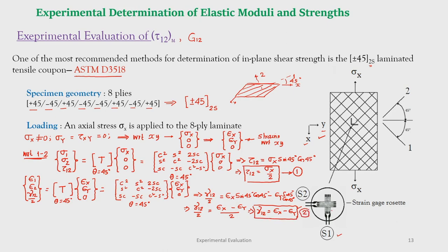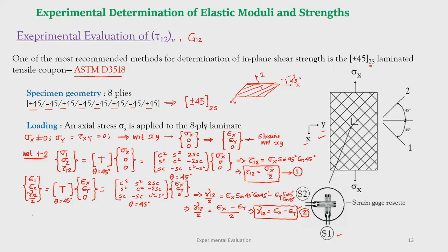Okay. That means we have applied a stress sigma x and therefore we know what is tau 1 2. What is tau 1 2? Sigma x by 2. And from the two strain gauge readings, we get epsilon x and epsilon y. Knowing those two strain gauge readings, we know what is gamma 1 2 also. Gamma 1 2 is nothing but epsilon x minus epsilon y. Okay. Now, by definition,